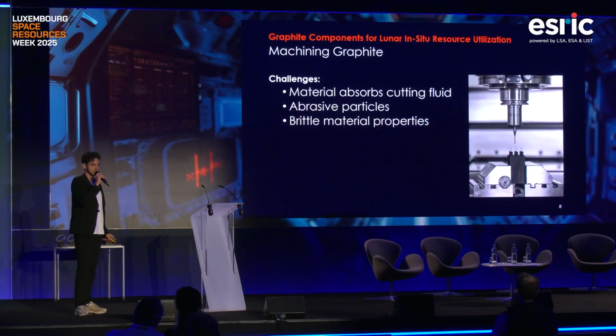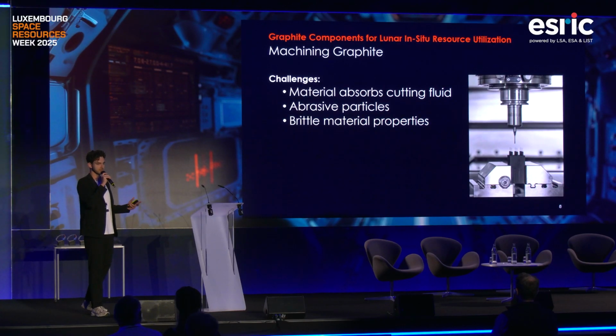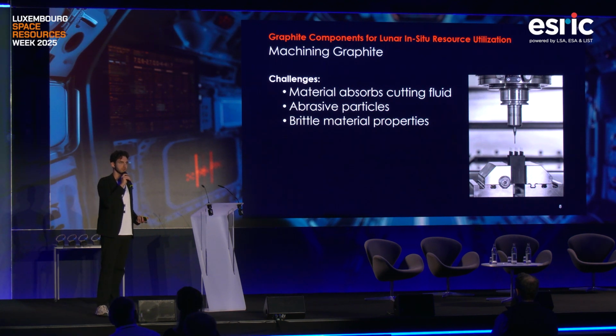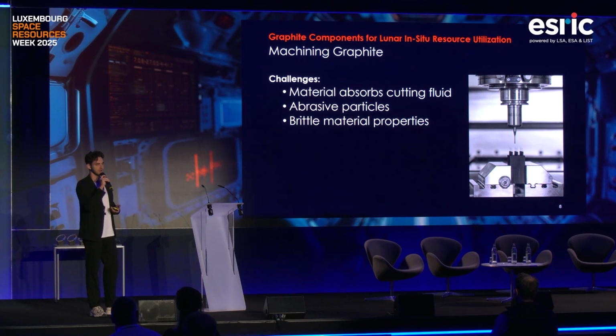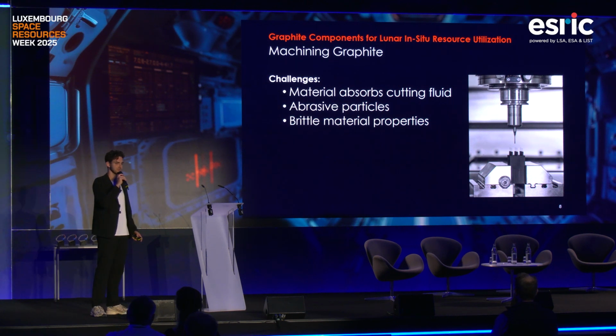So let's move on to actually machining graphite. As I said before, graphite is basically a compacted carbon matrix. When you start cutting it, graphite is quite brittle and also quite soft, actually, but the individual particles that you create while machining it are very abrasive. And the material itself is quite porous, so it acts like a sponge, and you can't use cutting fluid like you would on, for example, metals, because on the one hand, the material would absorb the cutting fluid, and on the other hand, the abrasive particles and the cutting fluid together would create a very abrasive slurry that would then